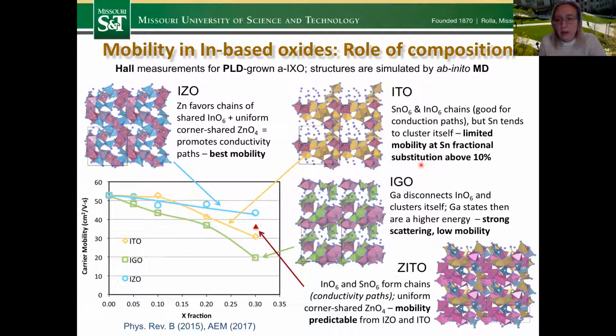As tin fraction substitution increases above 10%, mobility drops significantly, and then gallium disconnects the InO6 and clusters itself. So we have a very strong scattering and low mobility, and mobility goes down quite significantly among these three. So here we can place also Zito, and actually we can predict the mobility, what we would expect just based on this morphology in different compositions.